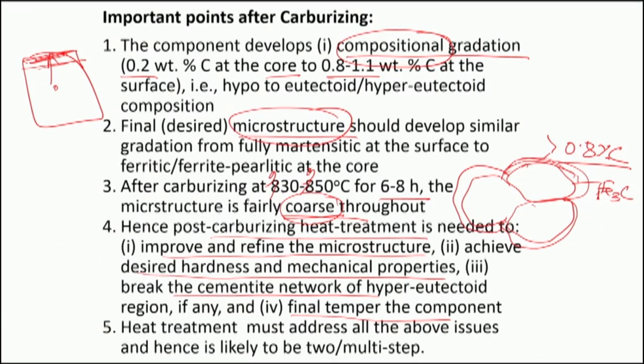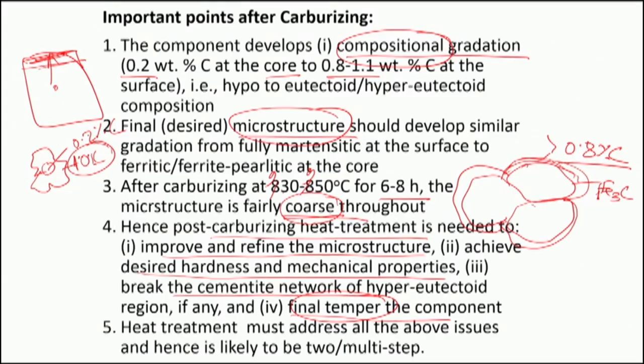Keeping all these things in mind, we may require a post-processing heat treatment — that is a final tempering treatment. Now imagine that this is a component that we have carburized, where the core is 0.2 percent and the surface is about 1 percent carbon. Obviously, we are talking as if about two different steels merged into one. For the 0.1–0.2 percent carbon core we harden from above the AC3 temperature, whereas for the high-carbon surface we harden from above AC1. How do we match these two conflicting situations?